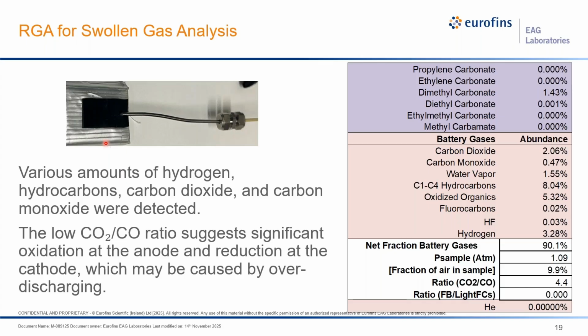And then there is a lot of information in this analysis, but the key thing that we are focusing on is to look for the hydrogen content, because one of the common reasons for batteries to fail is moisture ingress. So if the moisture is causing this battery to be swollen, then the hydrogen content in the swollen case should be much higher, more than 50%, which is not the case in this one. So in this particular example, RGA helps us see that moisture ingress is not related to the failure mode for this one.